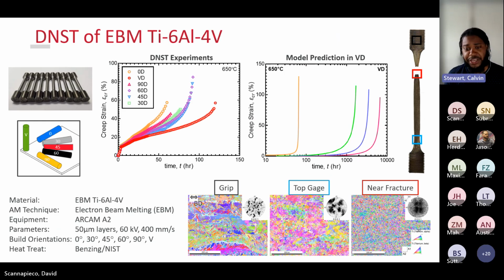So for this study, we went ahead and studied AM material, electron beam melted Ti-64. We did these DNST experiments, dynamically decreasing load. And we studied samples that were printed in different build orientations. Analyzing the experiments, we came up with metrics, things like rupture time, minimum creep rate, ductility, as well as strain energy dissipation, an energy-based term, to make accept, reject decisions about which orientation is best.